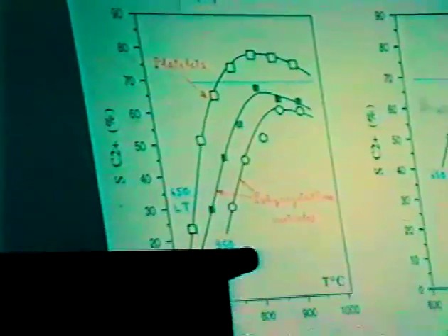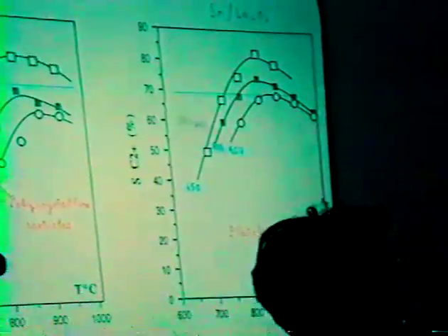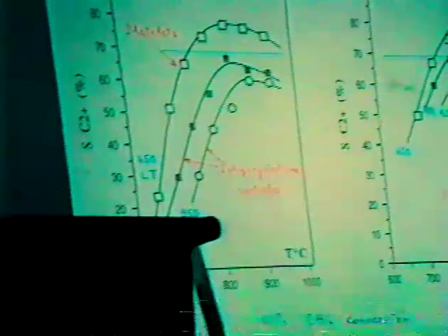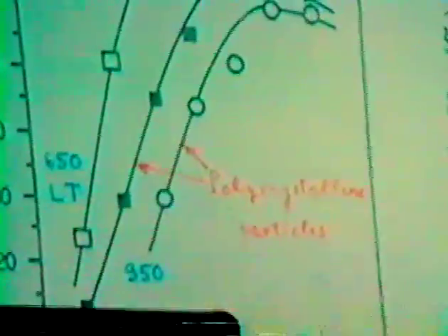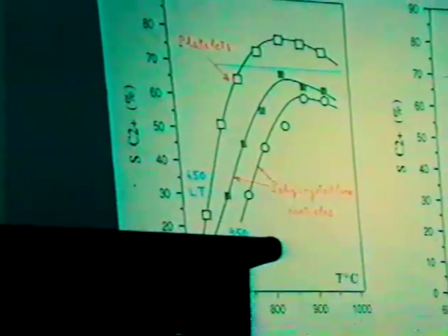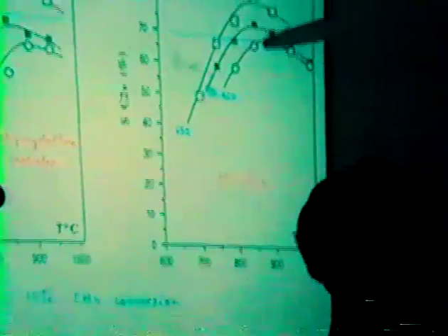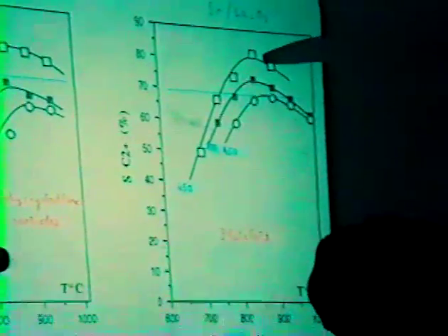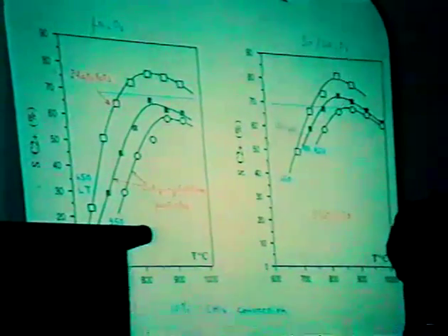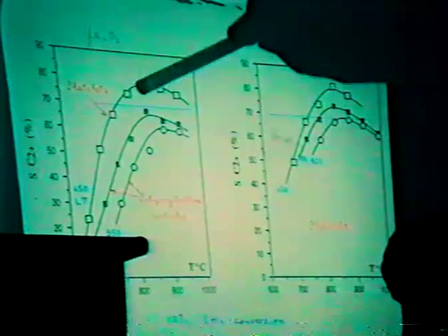Here I have represented the plots for the two catalysts, the selectivity curves at isoconversion of methane, at 10% conversion of methane. In blue, I have indicated the temperature of the pretreatment. You can see first that the lower the pretreatment, the higher the selectivity in C2+. Secondly, the selectivity of the strontium-doped catalysts is better than that of the lanthanum oxide, because for the free pretreatment, they are above this line.